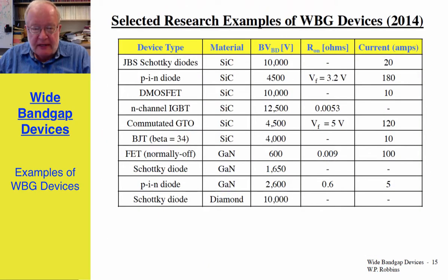Here are some other examples of devices that I found doing a quick search. Junction barrier Schottky diodes at 10,000 volts, a PIN diode at 4,500 volts, 180 amps, 3.2 forward voltage, a vertical MOSFET at 10,000 volts, 10 amps, an N-channel IGBT at 12,500 volts, on-state resistance of 5.3 milliohms, a commutated GTO at 4,500 volts, 120 amps, a bipolar junction transistor in silicon carbide at 4,000 volts and 10 amps, a normally off JFET in gallium nitride, 100 amps at 600 volts and 9 milliohms, and you can read the rest. There's even a diamond Schottky diode at 10,000 volts, but I couldn't find any other information about it.